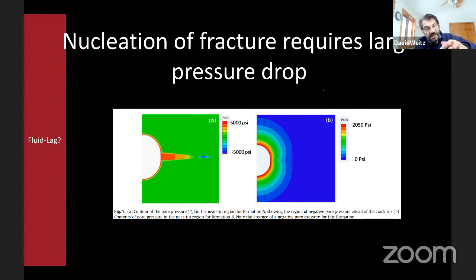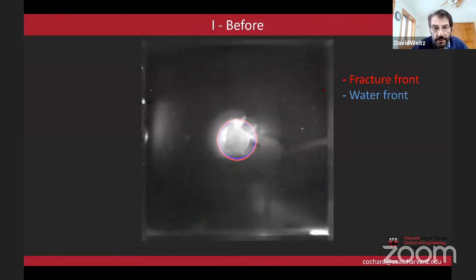When you have to have a nucleation, then the crack is way out in front of the fluid, and it takes some time for the fluid to catch up. In the other case, it happens much earlier. The fluid is always catching up. But in all cases, if you look carefully, it really looks like the crack is always moving faster and the fluid is trying to catch up. It's always pushing ahead. The crack front, the tip of the fracture is always ahead of the fluid.